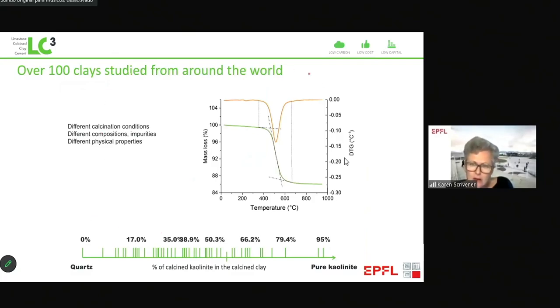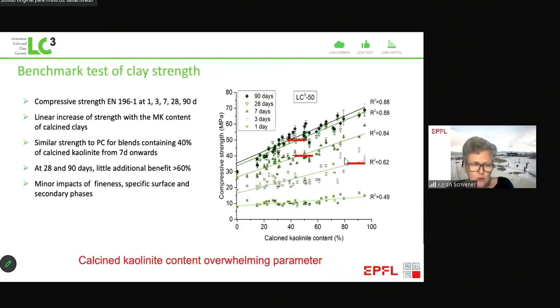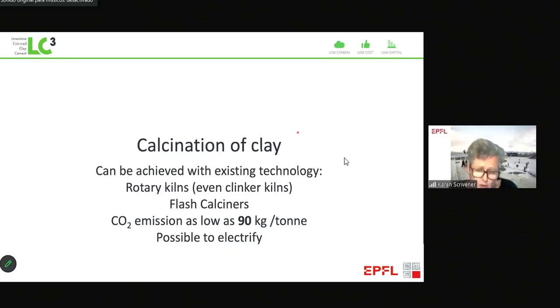And we can look at these different kaolinite types by looking at the weight loss. I won't talk much about this because I'm sure Fernando will talk in detail, and we can see the compressive strength correlates with the strength development. So when we look at calcination of the clay, the important thing is that this can be achieved with existing technology. We can use rotary kilns, we can even use adapted clinker kilns, and flash calcination, and the emissions can be as low as 90 kg, but in the range from 100 to 200 kilograms per ton.